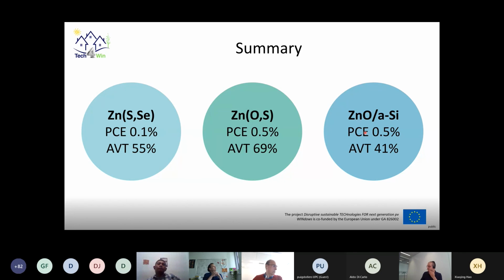And more recently, we also played with bringing in amorphous silicon as an extra layer, giving us directly an efficiency of 0.5% in the case of the thickest amorphous silicon layer, which can still be improved, we believe. And also this AVT, we should be able to improve as well.